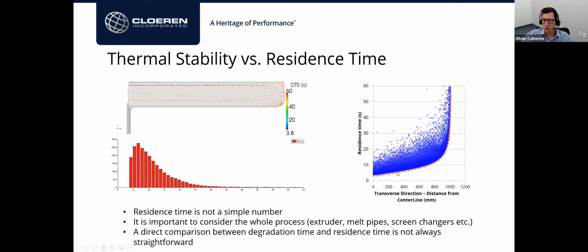And therefore, when we talk about a residence time, I'm always curious what people have in mind, but usually it's a much more complex notion than just a 2-minute residence time and so on and so forth. The other thing I want to point out is that when you look at a die and you have degraded material coming out, the die is the last piece of the hot portion of the extrusion system. You really have to consider the whole line's residence time.